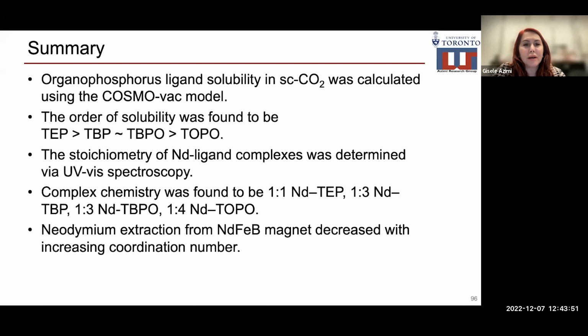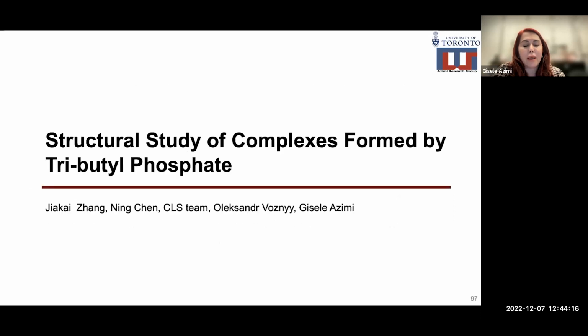The stoichiometry of neodymium ligand complexes was determined using UV-Vis spectroscopy. Complex chemistry was found to be 1:1 for neodymium TEP, 1:3 for neodymium TBP, 1:3 for neodymium TBPO, and 1:4 for neodymium TOPO. Neodymium extraction from neodymium iron boron magnet decreased with increasing coordination number.